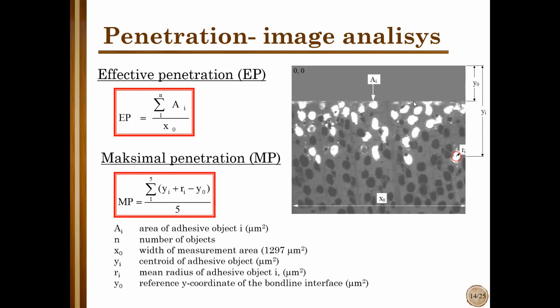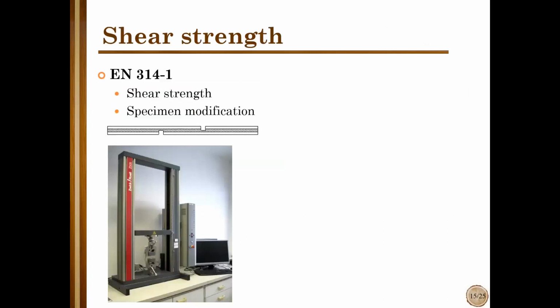Maximal penetration in a simple way is the deepest penetration of the adhesive into cell lumen. But because there is high variability, we took the 5 deepest spots and made an average of these. So effective and maximal penetrations were the ways we evaluated the adhesive penetration. And at the end, we wanted to correlate this to the shear strength.